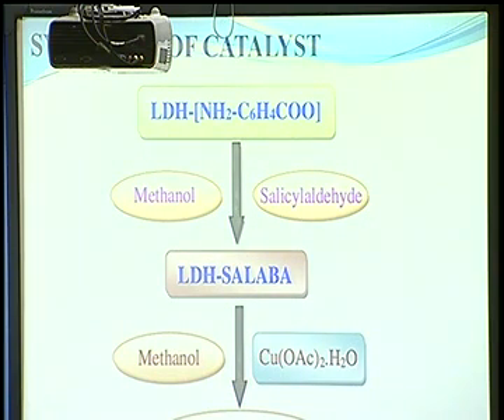This is the synthesis of catalyst, which has been done in 3 steps. First step is the synthesis of support, that is LDH NH2C6H4COO, which is made from zinc nitrate and aluminum nitrate with an alkaline solution of 4-aminobenzoic acid.